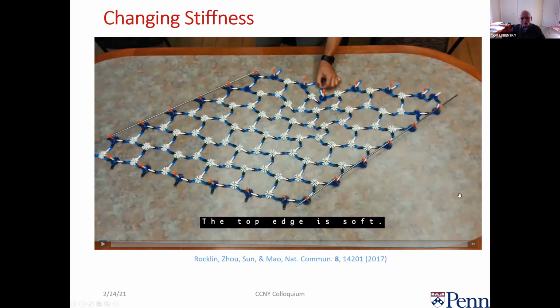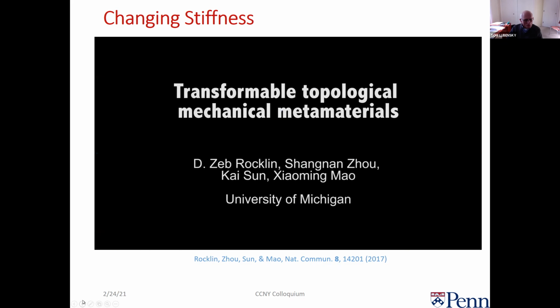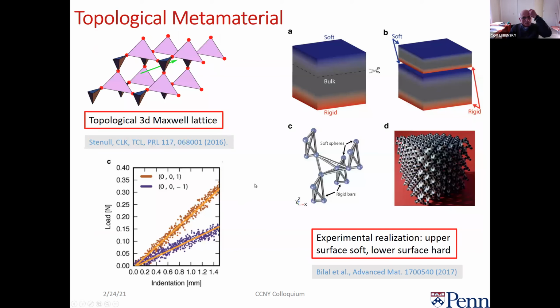So now that's a property which we don't see in nature unless you have some kind of a hybrid structure where you have a sponge at this side and a piece of metal at this side. Okay, so now I think I need to go to the next one. Now, one of the structures that we predicted was this distorted pyrochlore lattice. And the theoretical prediction is that this three-dimensional structure behaves in the same way as the two-dimensional structure. There's a top surface that becomes soft when it enters this topological state, and a bottom surface, which is rigid.